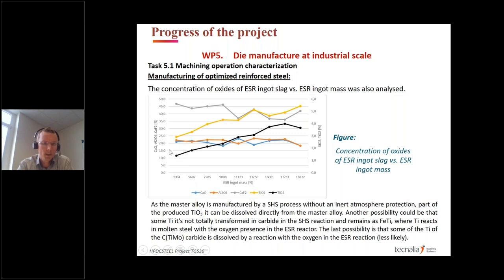What you can see here is that the gray line is the calcium fluoride line. So we see a slight decrease of the calcium fluoride over the remelting process, which is more or less known for an open ESR plant, which is given here at SWG. Then we have the yellow line, where we have an impact on the silica level. And then the alumina concentration and the lime concentration have been more or less constant. And what we can see here is an almost linear increase of the titanium oxide concentration of the slag over the ESR ingot mass. So that's why we came to the conclusion that